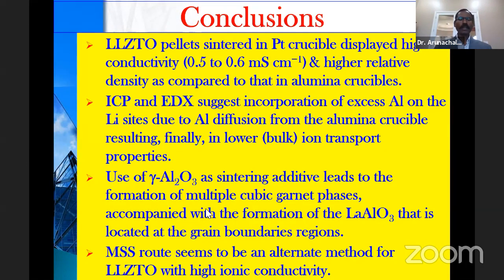Okay? And also when we use a sintering aid, that could lead to formation of different garnet phases along with the lanthanum aluminum oxide impurity. And that could get into the grain boundaries region. And again, that would lead to lower conductivity because the conductivity comes from both the bulk and also the surface and also the grain boundaries. Okay? So certainly the molten salt method can also be an alternative method for synthesizing lithium lanthanum zirconium tantalum oxide with higher conductivity.